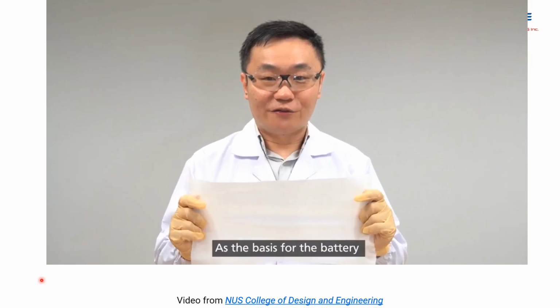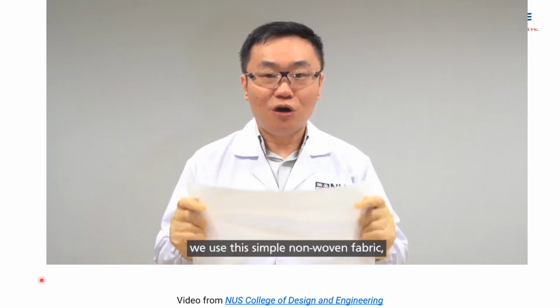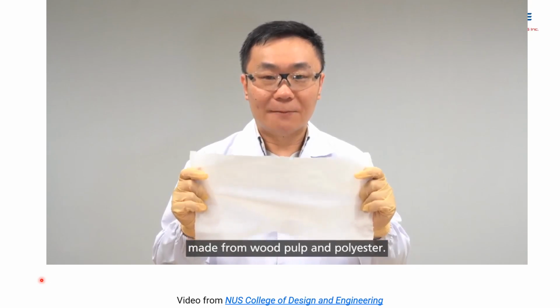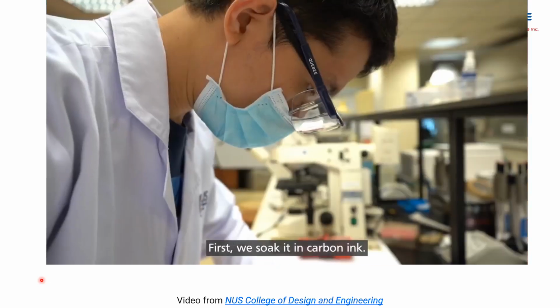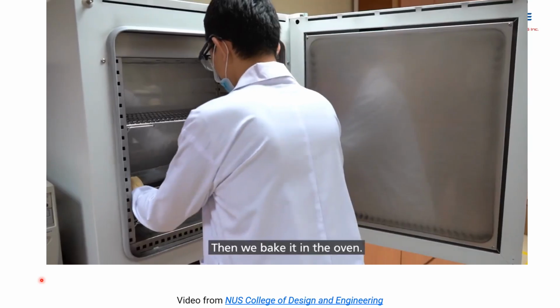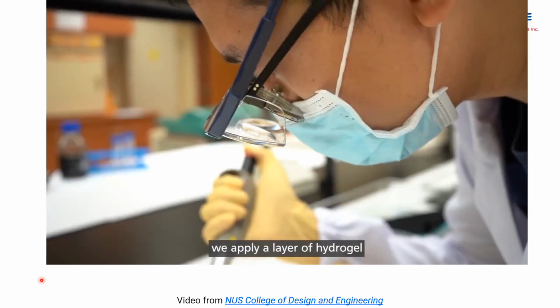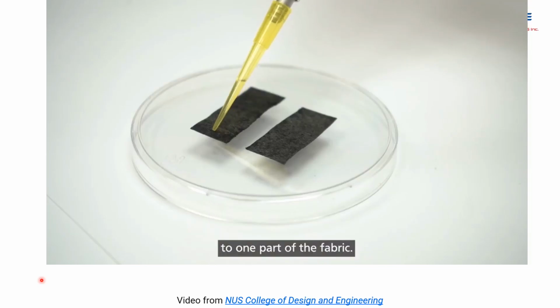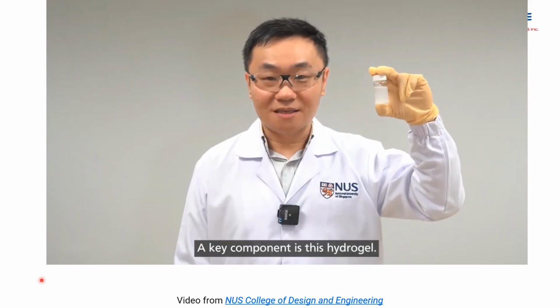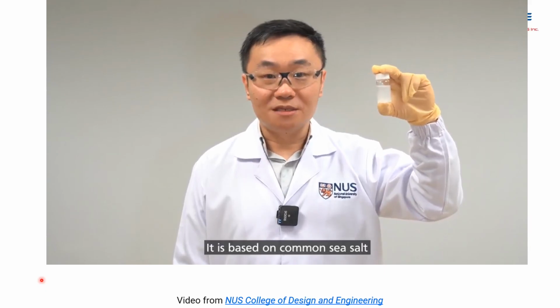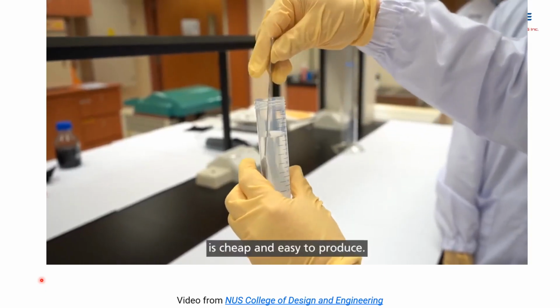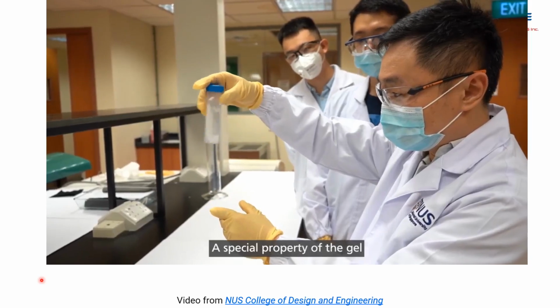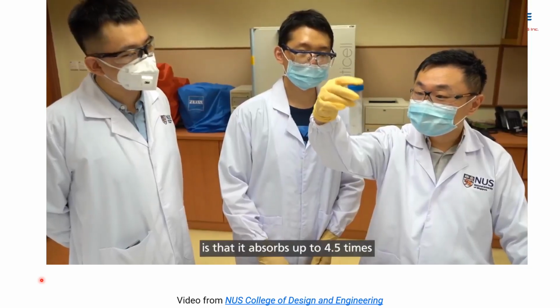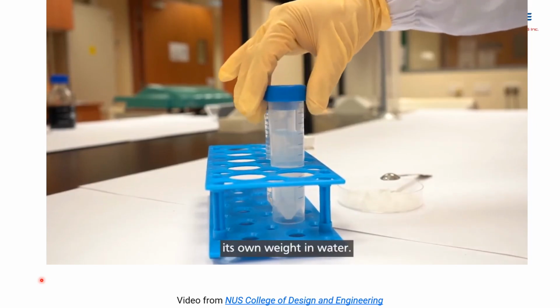As the basis for the battery, we use this simple non-woven fabric made from wood pulp and polyester. First, we soak it in carbon ink. Then, we bake it in the oven. And finally, we apply a layer of hydrogel to one part of the fabric. A key component is this hydrogel. It is based on common sea salt, which, like the rest of the device, is cheap and easy to produce. A special property of the gel is that it absorbs up to 4.5 times its own weight in water.